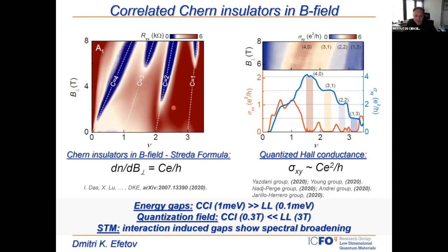And the reason we identify these experimental features as Chern insulators is really that they follow this diagonal line in the B to n phase diagram, which is given by this Streda formula. And of course, we measure quantized conductance in the Hall measurements, so we can really define a very robust Chern number to each of those states.